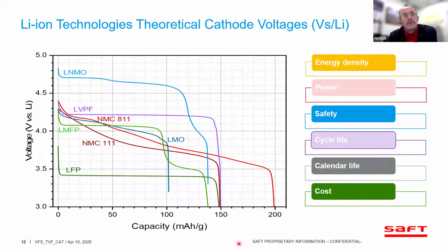So let's look more into the voltage side. You have chemistries that we saw earlier. This is against lithium metal, which is kind of a reference electrode in a way. So this is just the cathode side. But you can see a huge variability of voltage behavior throughout the discharge of your battery capacity. You see LNMO very, very high. That signals a very high energy capability, because power is voltage times current. So if you have a very high voltage, naturally you have very high energy in your system. LVPF also sticks out and is very interesting. And you have the more traditional NMC or LFP that evolve at very different voltages.